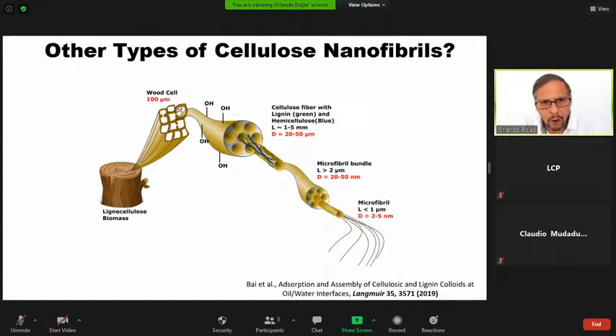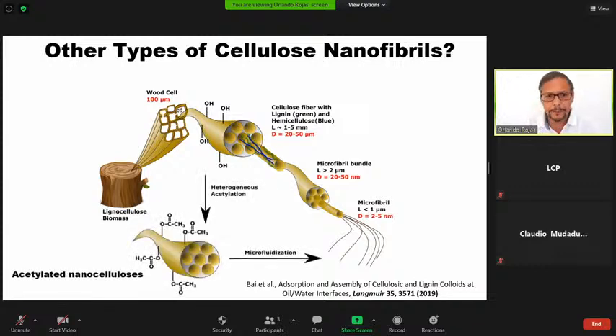Now, are there other types of cellulose nanofibrils? I think this is important because not all the properties of cellulose nanofibrils fit the specifications and demands of industry. For instance, the hydrophilicity has always been an issue for cellulose-based materials. And for that reason, I bring up the case of acetylated nanocelluloses. This is very important because if you think about the recent developments that we see, for instance, in Japan and the nanocellulose vehicle concept as an example, cars that are being produced with components made from nanocellulose. Many of those nanomaterials are really esterified nanocelluloses, for instance, by acetylation or other